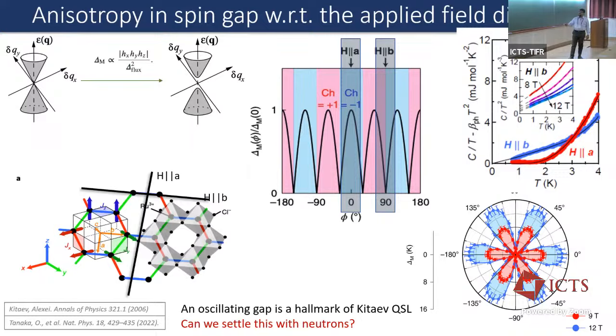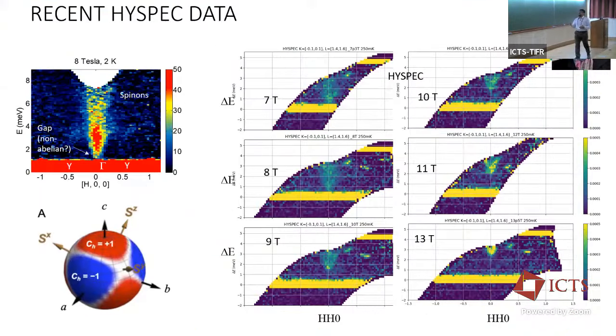They summed up that behavior in this plot here, where you have Chern number minus one, you see a gap, you have Chern number plus one, you see a gap, but when the Chern number is zero, where you have the transition, you don't see the gap. It was published in Nature Physics, and that's a hallmark of the Kitaev QSL. But then the question was, can we settle it with neutrons? Turns out that's something we have been doing.